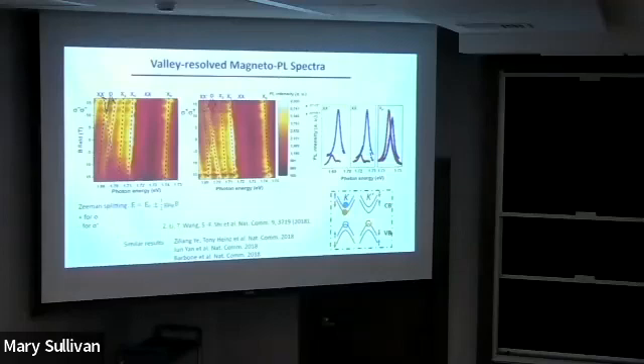One thing I want to emphasize is that if you look at the chart, biexciton by nature has a fairly small threshold because if you look at this four-quantum particle, it's one electron-hole pair here and another electron-hole pair here. As we will discuss later, both of these electron-hole pairs are dark excitons. As a result, they have a longer lifetime and very large density compared to exciton. So it's very easy to form this kind of quasi-particle in this system compared to the traditional semiconductors.